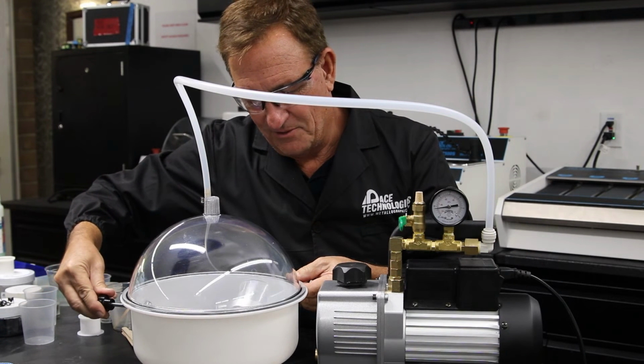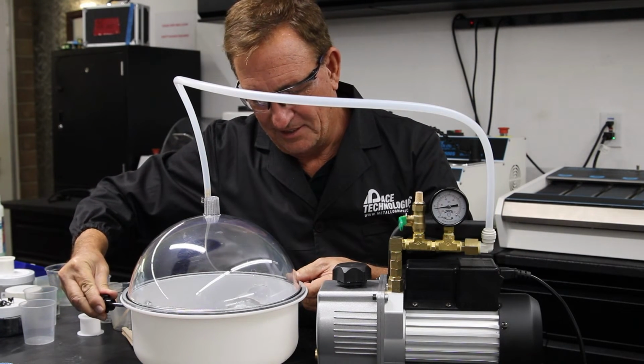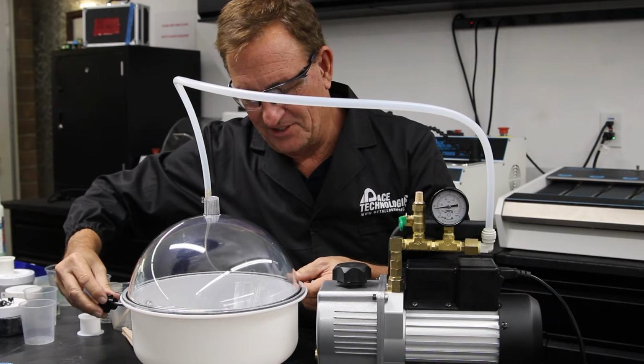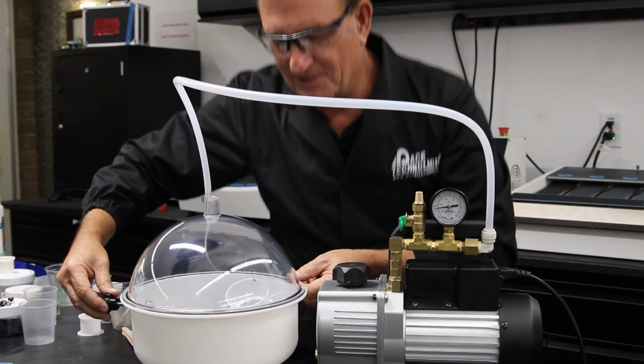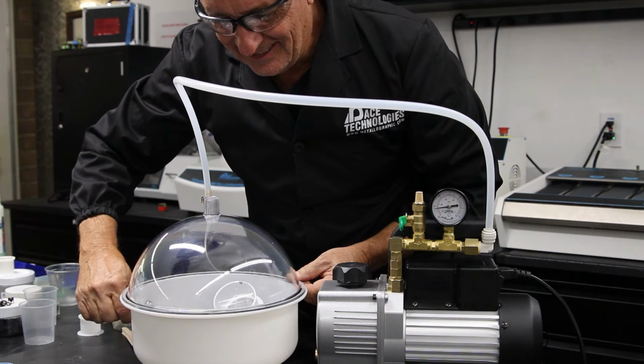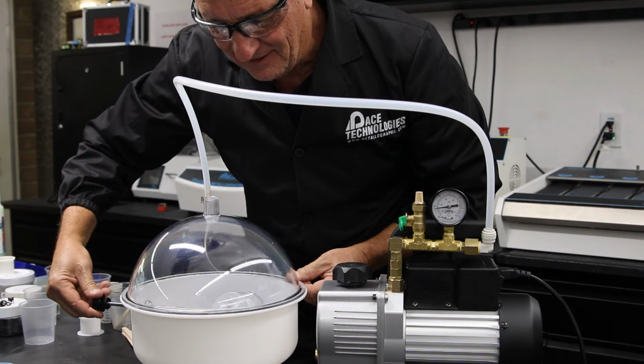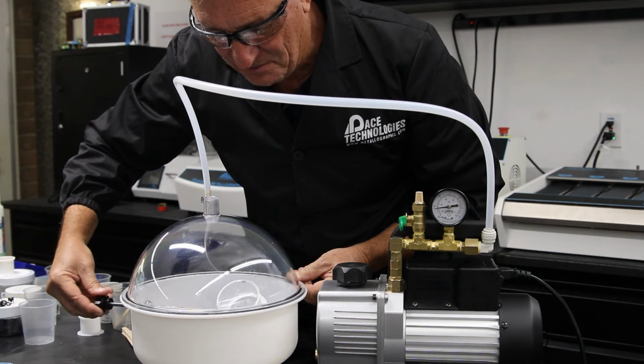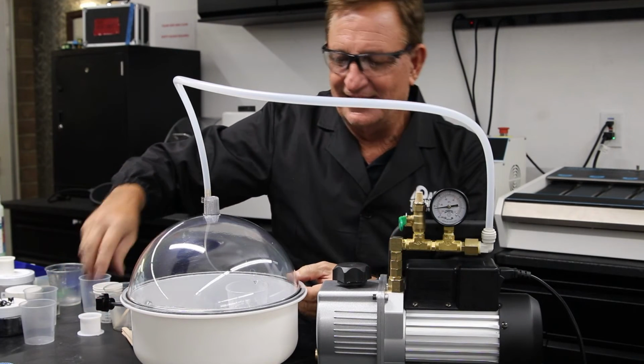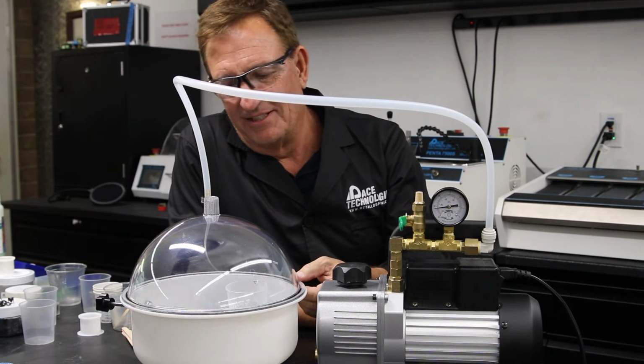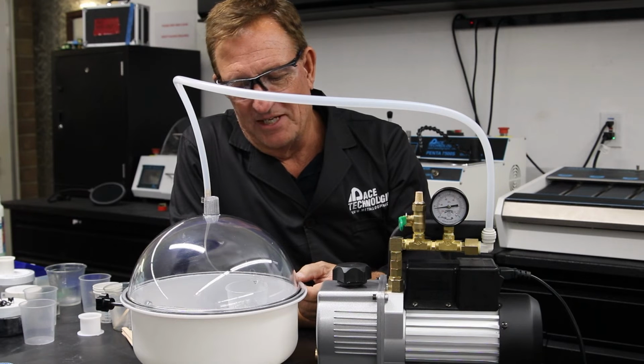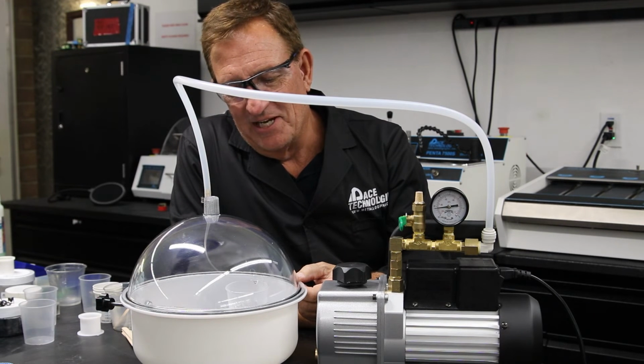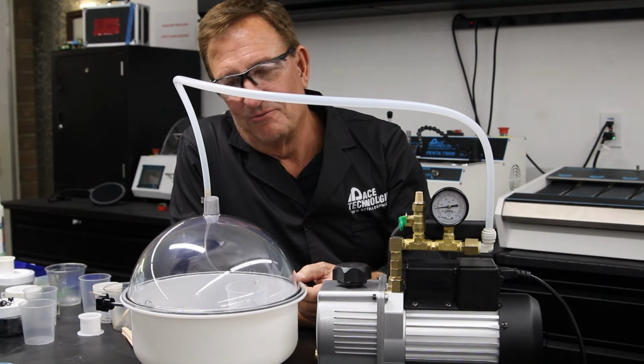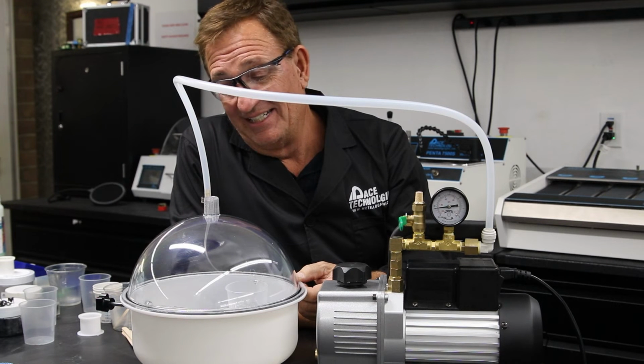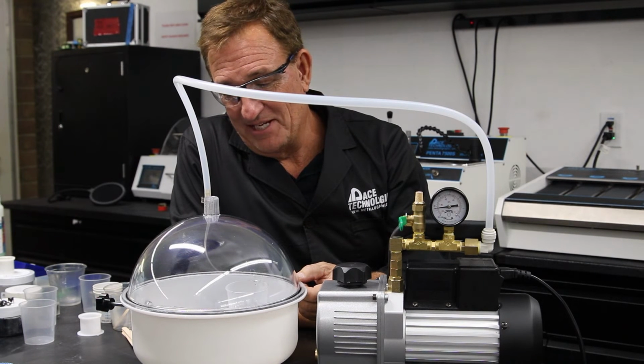The one thing that we don't want to do is pull the vacuum for too long, because it starts to cause the resin to degas. It's known as Henry's law, which states that the solubility of a gas in a liquid is proportional to the partial pressure above the liquid as well. So if you pull a vacuum, you will start degassing the resin. It's like opening a Coke bottle, and you get all the gas that comes out.